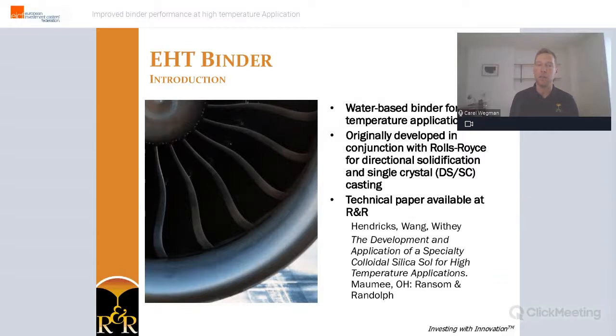Well, technological capabilities and requirements of the investment casting process continue to evolve. Requirements on the ceramic shell are getting more and more demanding, especially the aerospace industry with its blade and vane segments put great demands on the shell system. Both directional solidification and single crystal casting processes expose the shell to high temperatures.